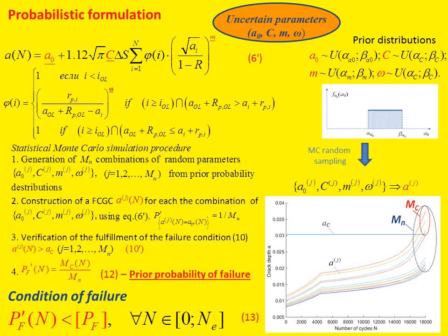After that, the probability of fatigue failure for a current number of loading cycles n can be determined as the ratio of the number of curves in our sample that cross the horizontal line of AC within the specified range of cycles to the total number of curves in the sample.